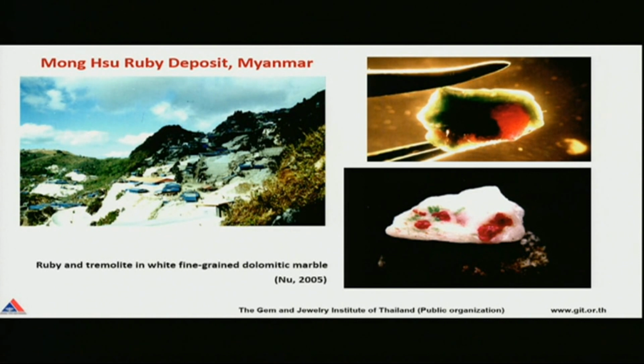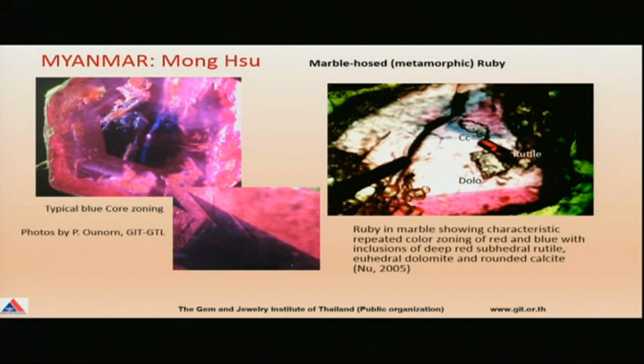And now we move to the Mong Hsu ruby deposit. They are really mined from the primary deposit, actually mined from fine-grained dolomitic marble. Okay, this is an example of the ruby hosted in fine-grained dolomitic marble with a little bit of tremolite. And also this is a rough sample with a greenish rim. The typical feature of Mong Hsu is a dark blue core underneath, which can be heat treated to a lighter color, or also the blue patch. That's very unique for this place.